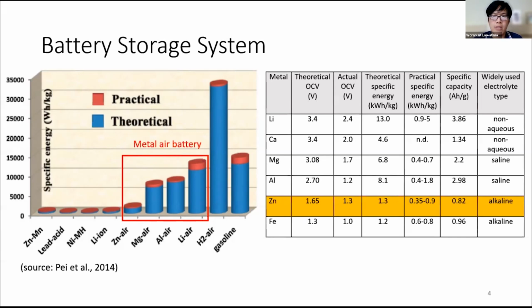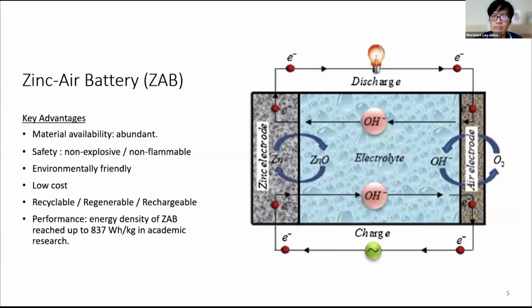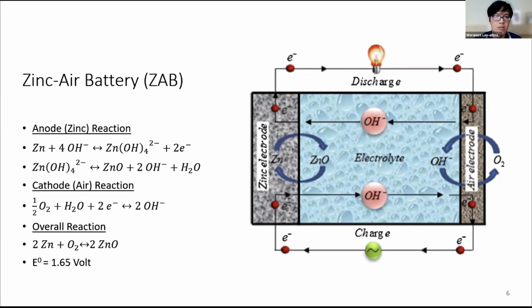Specific energy of zinc air battery has the smallest gap between theoretical and practical values. And it uses an alkali electrolyte, which is a very common electrolyte and easy to operate. The key advantages are that zinc metal is very abundant. The battery is safe and does not explode, so it is friendly to the environment. And next, zinc can be regenerated by various procedures, especially electrochemical recharge. Therefore, the zinc air battery is a rechargeable battery. Also, the performance of zinc air battery progresses every year, and now the energy density of zinc air battery has been able to reach up to 800 watt-hours per kilogram.